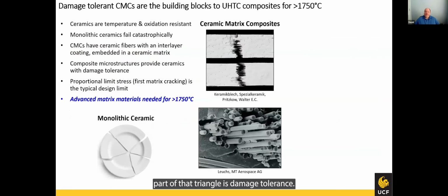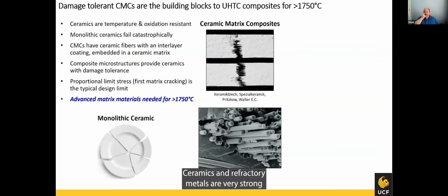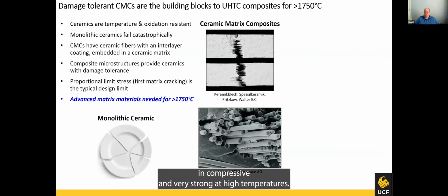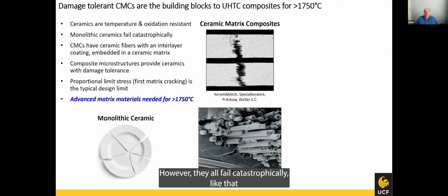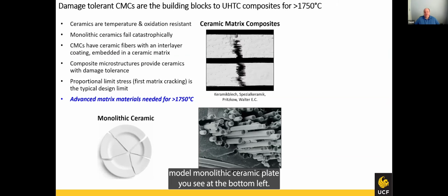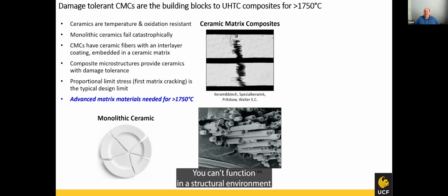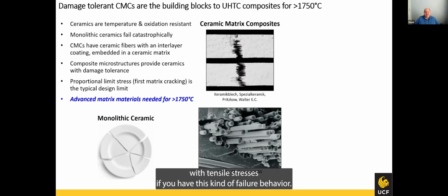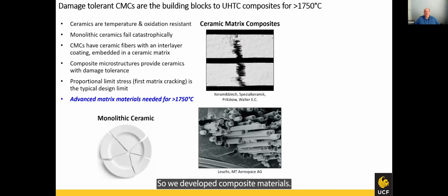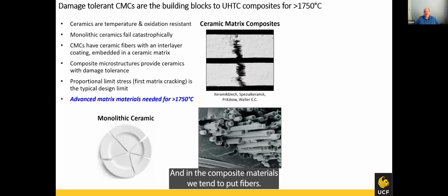So the third part of that triangle is damage tolerance. Ceramics and refractory metals are very strong in compression and very strong at high temperatures. However, they all fail catastrophically, like that monolithic ceramic plate you see at the bottom left. This has been the problem with ceramics and refractory metals for decades. You can't function in a structural environment with tensile stresses if you have this kind of failure behavior. So we develop composite materials, and in the composite materials, we tend to put fibers. That's the current way of doing it.